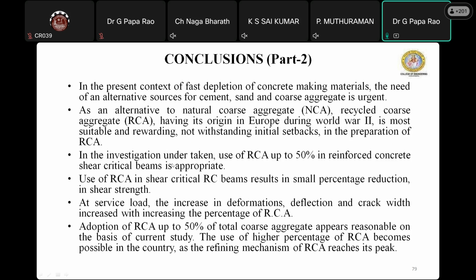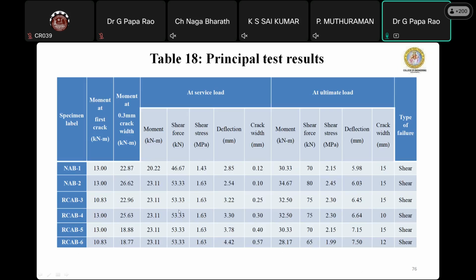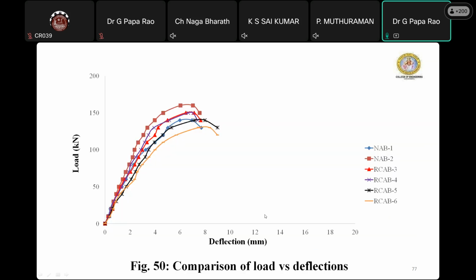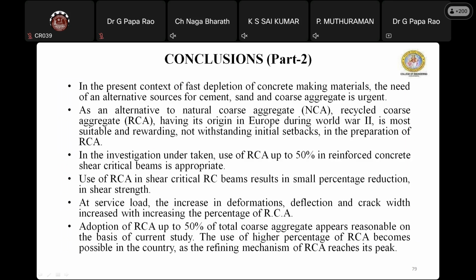So in the investigation undertaken, RCA, that is recycled coarse aggregate, up to 50% in reinforced concrete shear critical beams is appropriate, because at 50% the crack widths are meeting the permissible crack width of 0.3 mm. Therefore, use of RCA up to 50% in reinforced concrete shear critical beams is appropriate. Use of recycled coarse aggregate in shear critical RC beams results in a small percentage reduction in shear strength. At service load, deformations, deflection and crack width increased with increasing percentage of RCA.